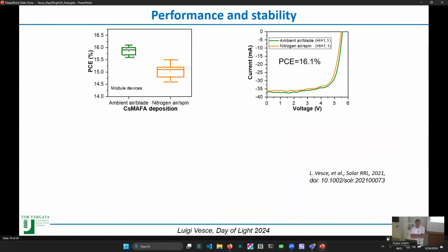Here you have the modules. You have 5 modules for each deposition technique. You can see that in this case, the performance of the bladed modules is better with respect to the performance of the spin coated ones, because of the homogeneity that we get in the deposition of the perovskite. And so it's better both in champion efficiency and in the statistics.